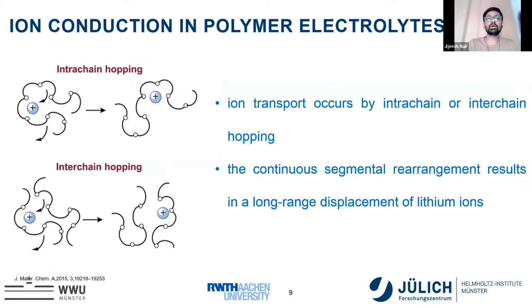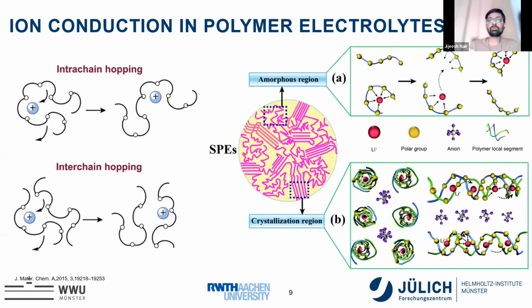For example, in a polymer electrolyte, especially in the amorphous phase, the lithium ions can mobilize either within the polymer chain or from one polymer chain to another polymer chain. So this is called intra-chain or inter-chain hopping, especially because, as I mentioned, polymer is a semi-crystalline material. It has amorphous nature and crystalline nature. And the crystalline part of polymer, especially in PEO, conducts differently than the amorphous phase, in which the segmental motion plays a big role. So the glass transition temperature of the polymer will play a big role in modifying the polymer electrolyte characteristics.